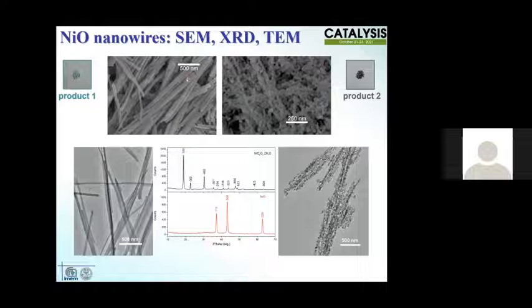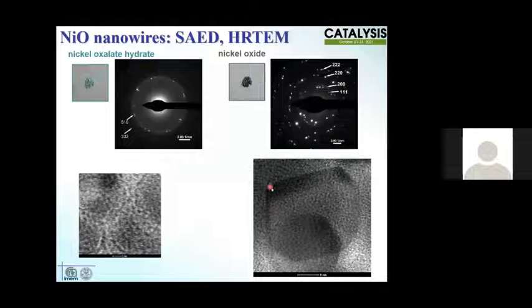In this case, I was working with a material that, after hydrothermal growth and a thermal annealing, was getting these polycrystalline nickel oxide nanowires. And you can see that they are quite homogeneous and made after the thermal annealing of these small particles that are 15, 20 nanometers in diameter.